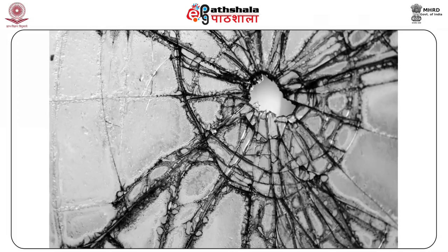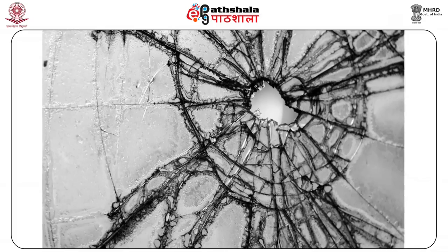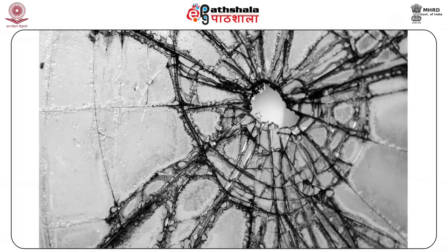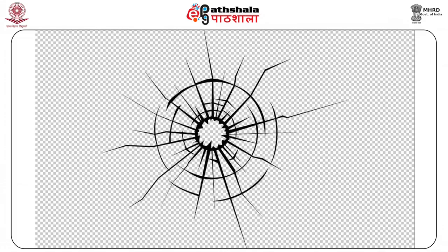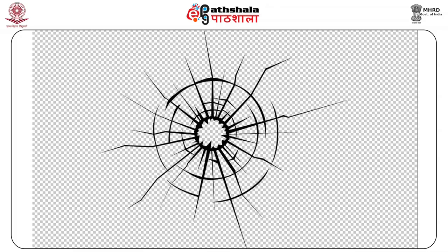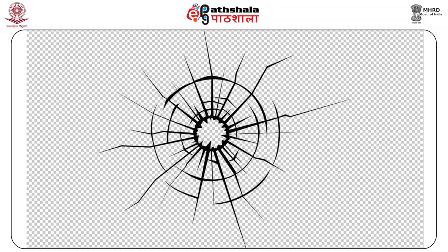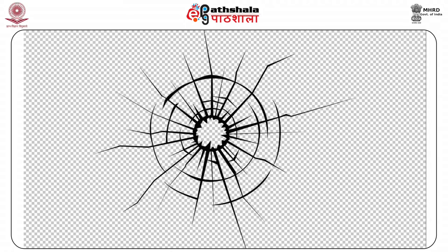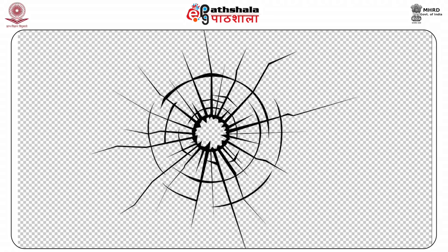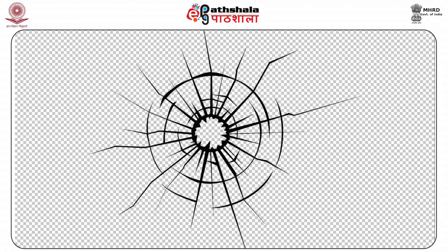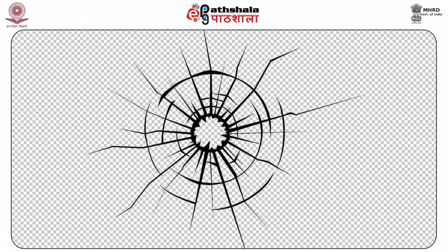Laminated glass as target and its penetration by projectile. Laminated glass consists of two sheets of glass bonded together with a plastic film. When it is struck by a bullet, it will first bulge away from the site of impact. This will cause a series of radial cracks. As the glass continues to bulge, concentric cracks are produced, the quantity of which is determined by the energy given up by the bullet to the glass. The quantity of crushed glass round the periphery of the entrance hole is also a function of the energy given up.